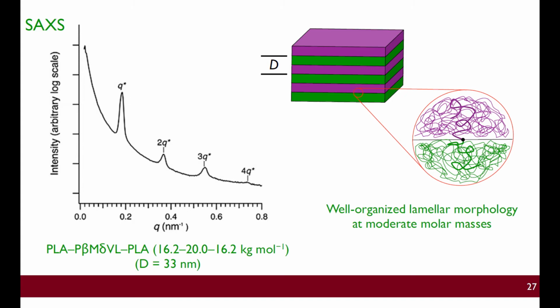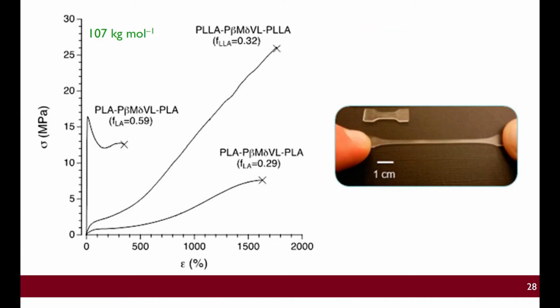But probably most importantly, from a mechanical performance standpoint, they behave just like the materials that I told you came from petroleum, the styrene, isoprene, styrene ones. So for example, if you look at this polymer right here, this is a stress strain curve. How much stress do you have to apply to a tensile bar like this to get a certain amount of strain, given in percent of its original length? It takes more and more stress to elongate the material, but it doesn't break until it's been elongated over 1,600% of its original length. Probably more importantly, the stress at which it breaks is over 25 megapascals, making this certainly quite competitive with its commercial petroleum-based analogs.